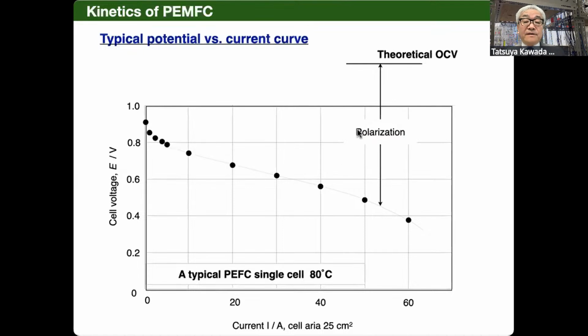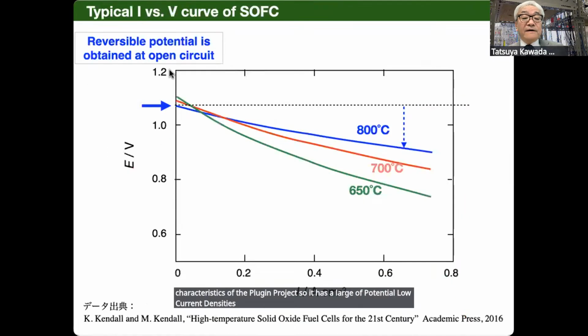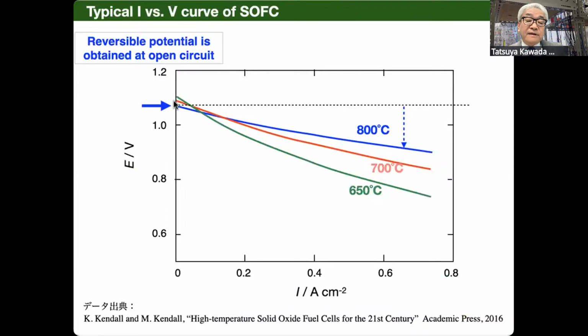So the important part was the difference of the kinetic or activation overpotential. This is a typical IV characteristic of the low temperature fuel cell. It has very large overpotential at low current densities. But solid oxide fuel cell does not have much overpotential around the open circuit voltage. So almost linearly, the current can be extracted. That is why we can have very high efficiency fuel cell systems.